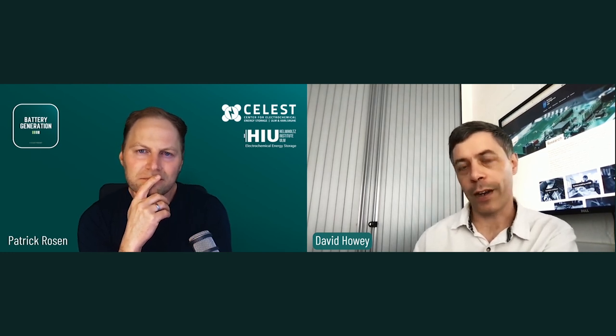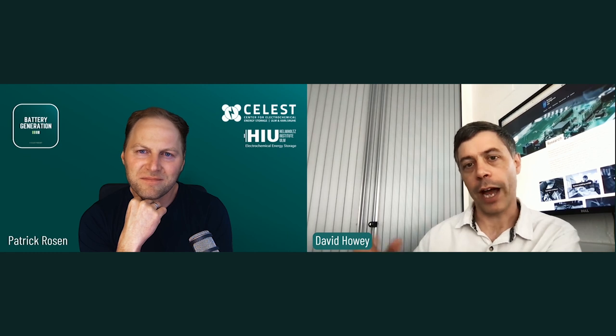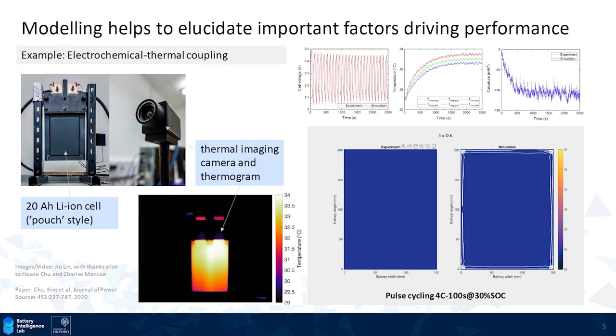It affects the battery behavior in a few different ways. So one way that it impacts behavior is by changing the reaction kinetics. So if we go to higher temperatures, everything kind of speeds up. You could say the battery performance improves. And what I mean by that is that the internal resistance drops or the internal overpotentials decrease at higher temperature. And that's good because the battery's generating less heat and everything's kind of running better. I think the downside of that is that all the side reactions that lead to capacity fade also increase at high temperature. So there's no free lunch. So temperature impacts internal resistance and therefore performance.